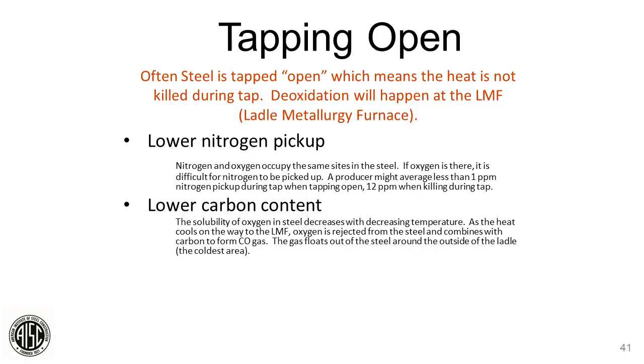So we have a process we call tap it open. It's the terminology we use now. It means we don't kill the heat. We don't put any deoxidizers in the steel at tap. We let it happen at the ladle metallurgical furnace. We do that for a couple reasons. One of our primary reasons is to lower the nitrogen pickup. If there's lots of oxygen in the liquid steel, it's less susceptible to absorption of nitrogen, increasing the nitrogen levels in our steel. And then lower the carbon content. Again, we want to keep our carbon as low as possible to achieve the properties we want as far as yield, tensile, and Charpy V-notch. Next slide.